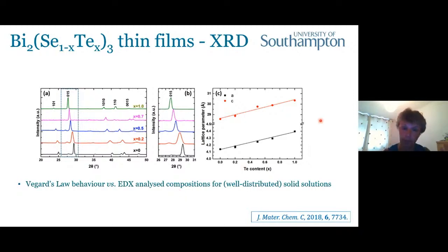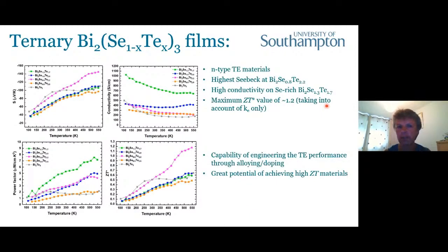So that's exactly the sort of scenario that we were hoping for. Again, we can use these to deposit these ternary films, and without going into the details of the thermoelectric measurements here, probably the most important thing to say is that we can generate N-type materials with a range of compositions, and we can see a variation in the thermoelectric properties, so we can optimize the thermoelectric properties based on that composition. And this work has actually just been recently published in the literature.